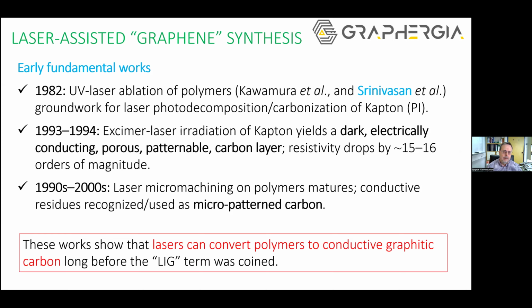So already in the 80s and the early 90s, we have some fundamental studies of UV laser ablation or excimer laser radiation of polymer materials and especially Kapton polyimide. The main idea at that time was to prepare conductive tracks on polymeric films. The researchers at that time were able to produce porous, electrically conductive, and patternable carbon layers on the surface of these polymers. So actually, these earlier studies established the groundwork for the laser-based transformation of polymers into conductive graphitic carbon structures. So you can understand that long ago, before the popularity of LIG, before the laser-induced graphene term was coined, the main physical and chemical principles were already emerging from such studies.